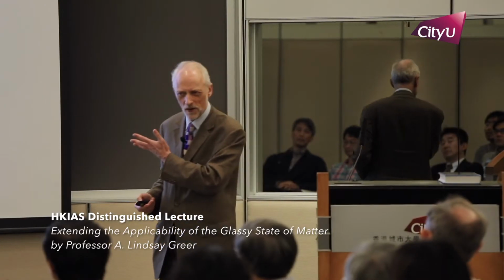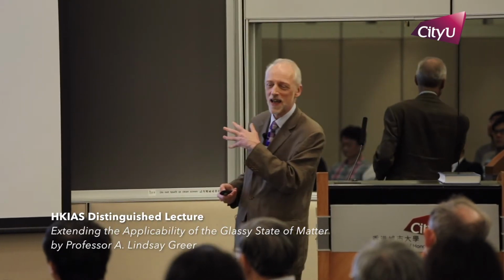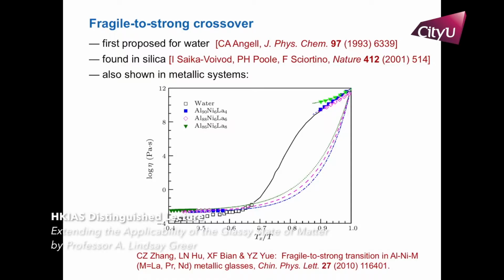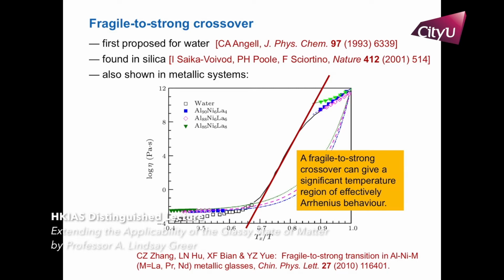So there's something funny going on here, where you're getting Arrhenius behavior of crystallization, this long straight line, in a region where you don't expect it. And we think what's going on is this: it's increasingly become clear that some systems are neither fragile nor strong, but both. They're fragile at high temperatures, strong at low temperatures, first identified or proposed for water itself, and then for some metallic systems, because that gives you a long bit of what is, to my mind, entirely accidental Arrhenius behavior in the middle. Not, if you like, a true Arrhenius behavior at all.